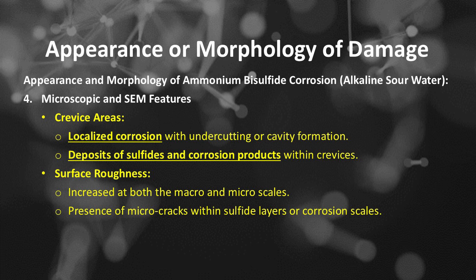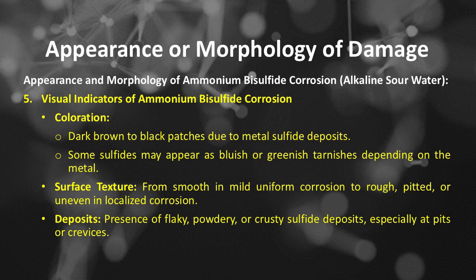The second of the microscopic and SEM features is crevice areas, which include localized corrosion with undercutting or cavity formation, and deposits of sulfides and corrosion products within crevices. The third is surface roughness, increased at both the macro and micro scales, with the presence of microcracks within sulfide layers or corrosion scales. Appearance and morphology of ammonium bisulfide corrosion or alkaline sour water.